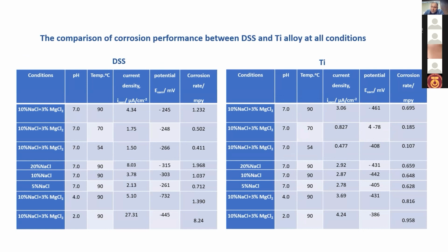In addition, the reason for this superiority of the titanium alloy over duplex stainless steel in regard to corrosion resistance is mainly that the main element in the titanium alloy is titanium, which forms titanium oxide. This titanium oxide is the counterpart of chromium oxide in protecting the base alloy from corrosion. But at the same time, duplex stainless steel can be an ideal alternative to titanium alloys because of its excellent corrosion resistance compared to conventional stainless steel, and its lower cost compared to titanium alloys.